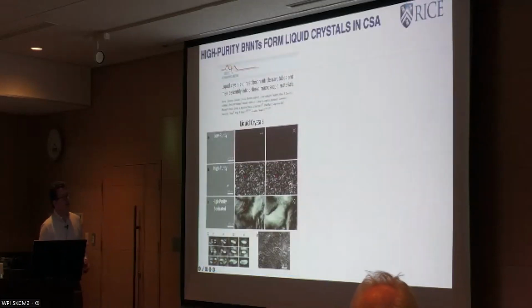And so when you go to higher concentration, you start forming liquid crystals. What you see is the purity of your sample is critical. This is a lower purity sample. When it gets purified, what you see is much larger liquid crystalline domains. Here, there's barely anything. But also what's interesting is that it looks like there's some sort of jelly structure or glassy structure, because you give it just a little sonication and these domains merge into much larger structures. You can find tactoids in these regions,